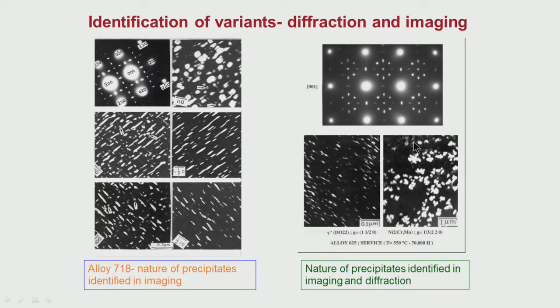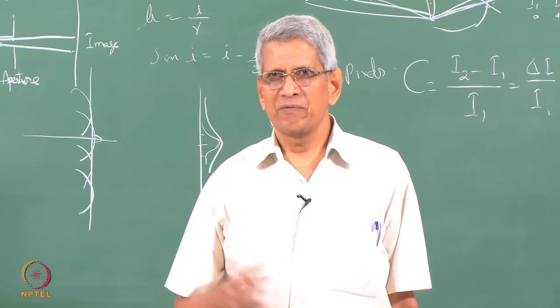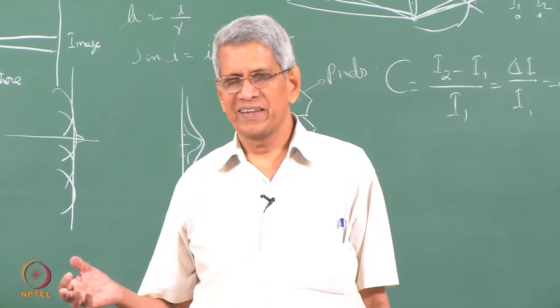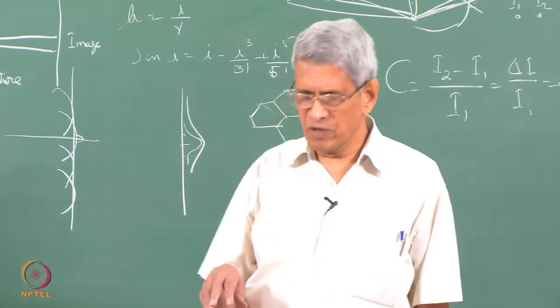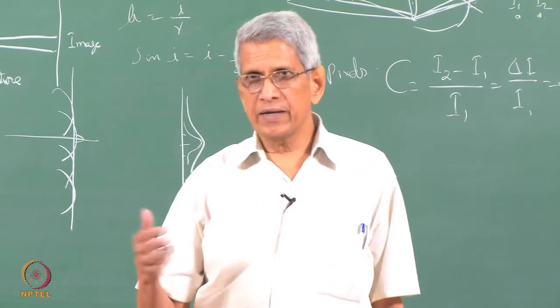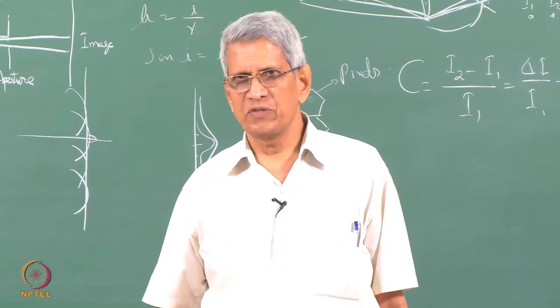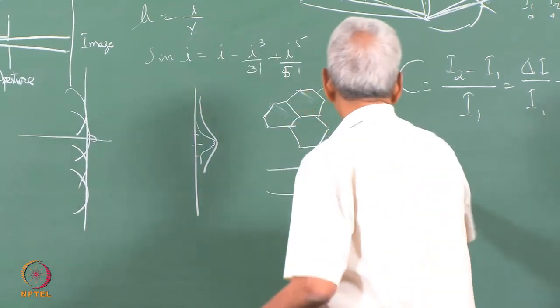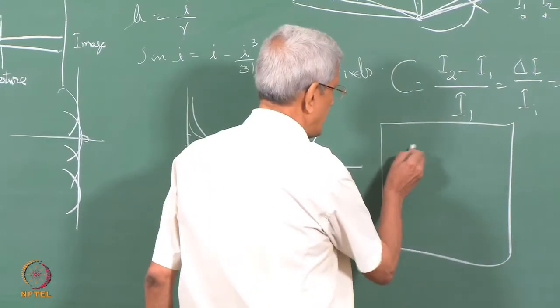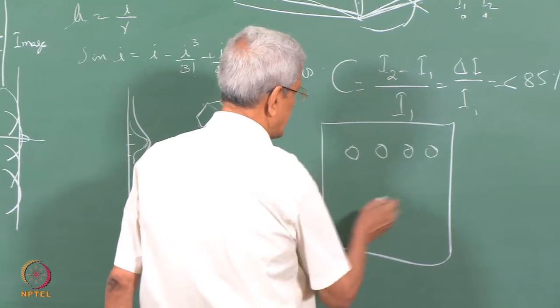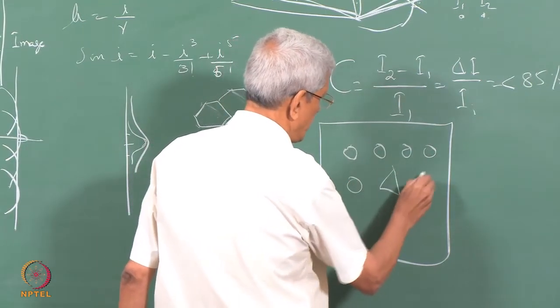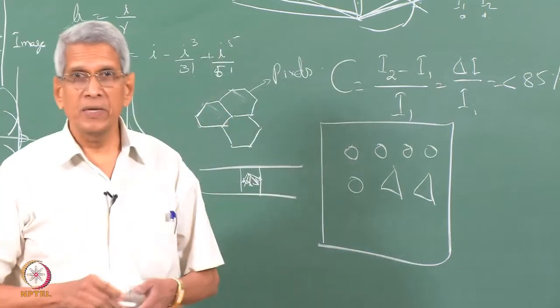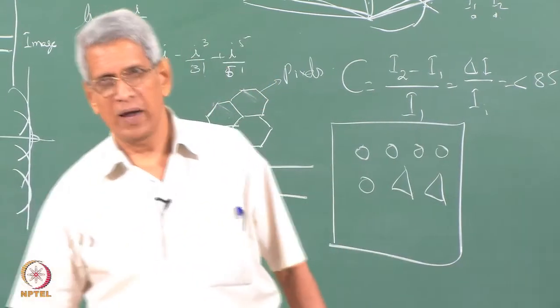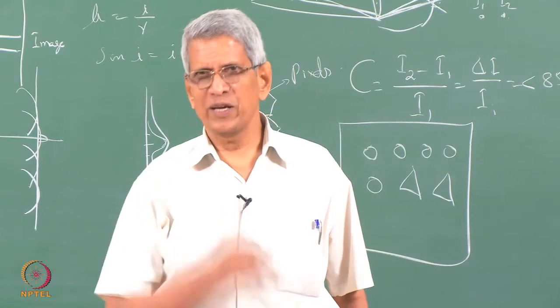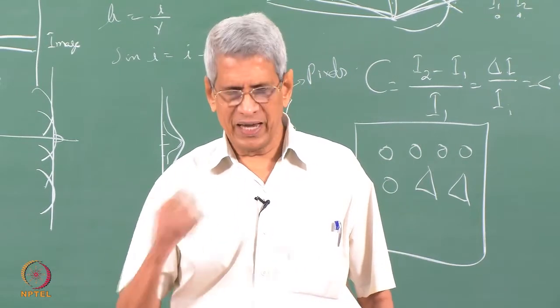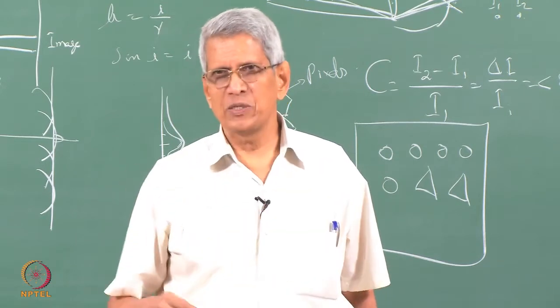Essentially what you can make out is that using a bright field image, we find that variation in contrast is there. That tells that there could be different types of phases present. And if there are morphological differences which we see in the pattern, because what may happen is that in some regions the precipitates appear like this, and some precipitates have a different shape. It's possible that this sort of shape may be due to another particle. By using a dark field image, we can try to find out what these precipitates are.